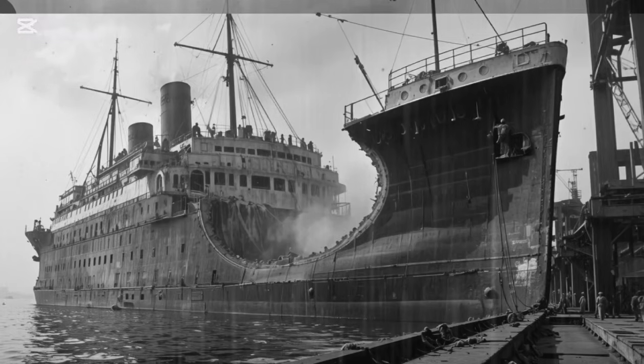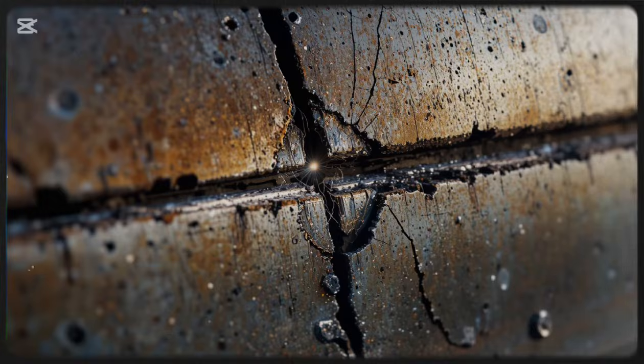Traditional riveted ships had thousands of individual rivets holding plates together. If a crack started, it would hit a rivet and stop. The rivet acted as a crack arrestor. But welded ships were different. The welds created continuous seams of metal. If a crack started in a weld, there was nothing to stop it. The crack could propagate across an entire section of the hull at incredible speed.